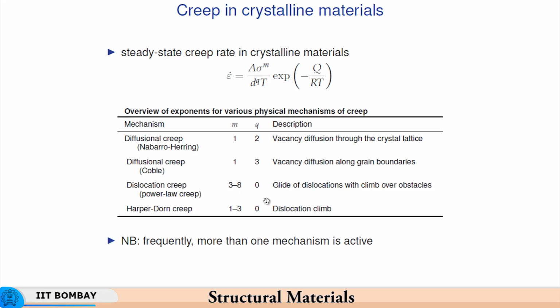For power law creep, there is dislocation activity. So, basically dislocations are the ones which are active, and therefore, this happens at relatively lower temperatures and relatively lower stresses. So, the dislocation glide takes place to climb, and after climbing over obstacles, the thermal part of the energy results in dislocation climb, and therefore, obstacles are avoided and dislocations continue to glide after climbing over the obstacle. So, this is how obstacles get circumvented and the creep strain continues unhindered. Harper-Dorn creep also we have seen, it is again due to dislocation climb,